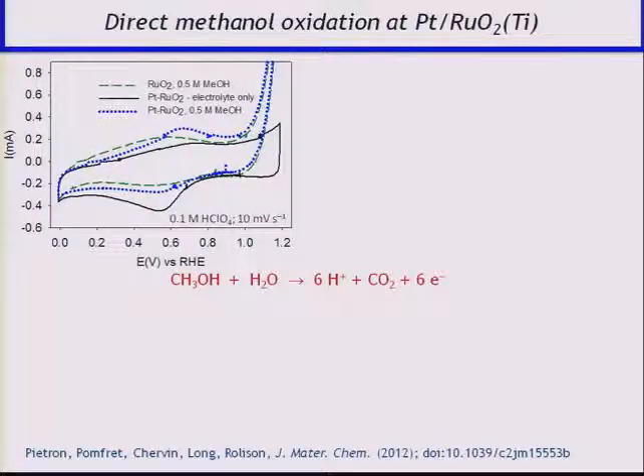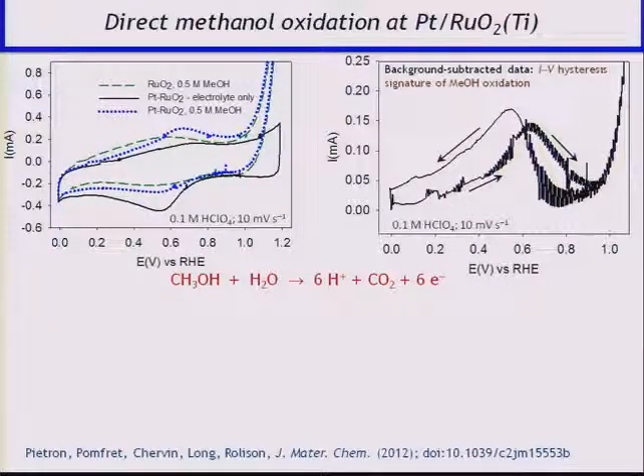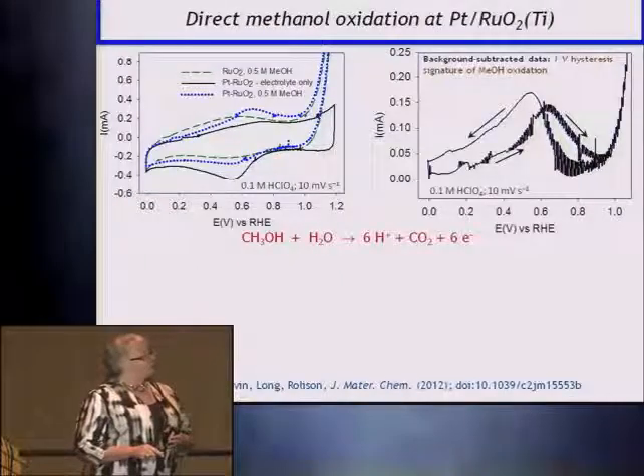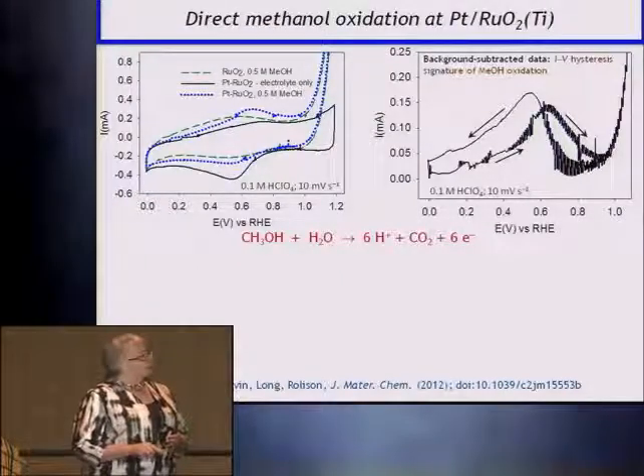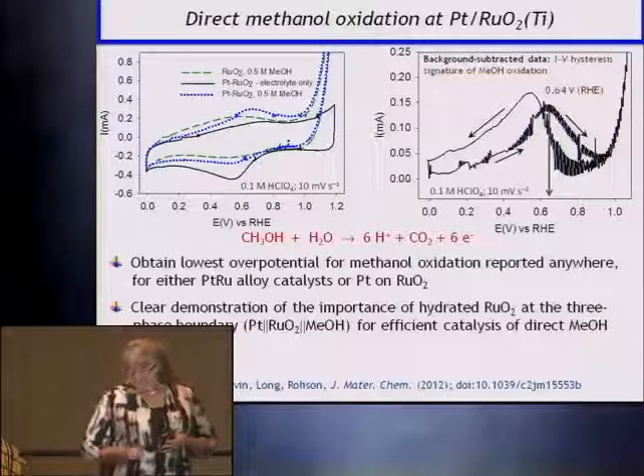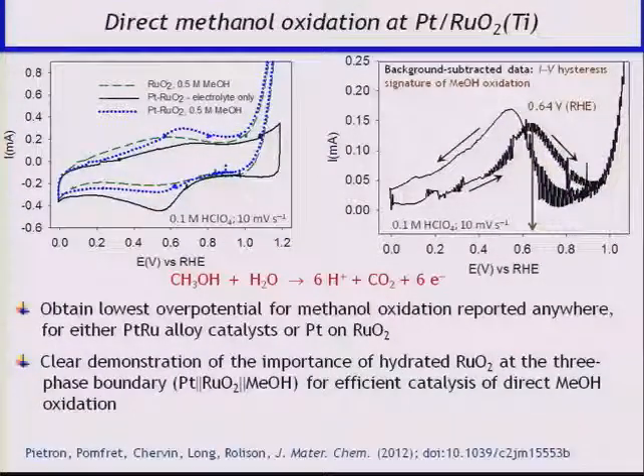Part of the problem is we have so much pseudocapacitance here. So if you background subtract that, you get the classic hysteretic voltammogram you expect for methanol at platinum. Forward-going sweep, return sweep. But now the potential is as good as it gets: 0.64 volts versus the reversible hydrogen electrode.